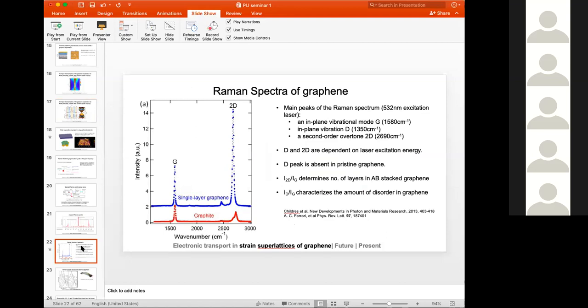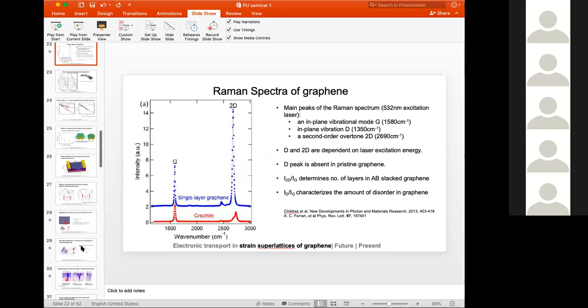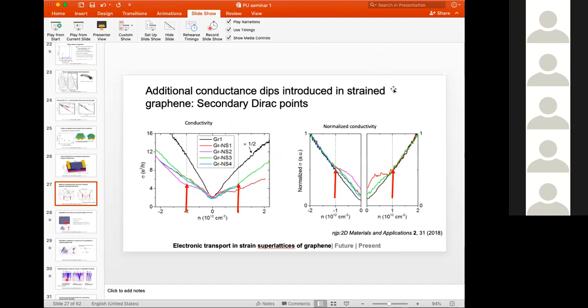But now the question to Preetha is going back to your data on the kink. I am of course aware of superlattice calculations when you have just potential fluctuations, but you have slightly more, which is you actually have gauge fluctuations which are varying on some particular length scale, which has a periodic character to it. Right? So my question was, have people actually looked at the theory and have you tried to match to some extent with that? I don't have the curve right now, but actually they have. We collaborated with some theory groups, and very prominently it shows the conductance dips with these gauge field effects taken into account. I think some of these references might help. Okay, yes, it has been looked into. Thanks.